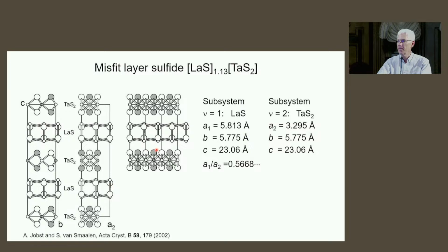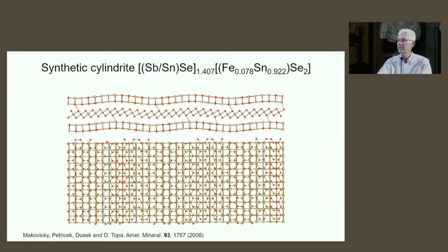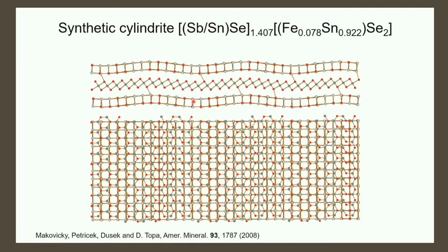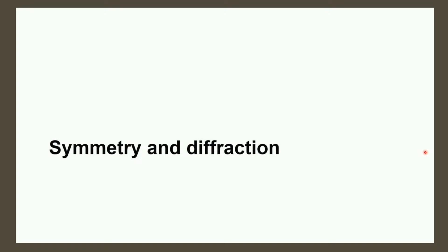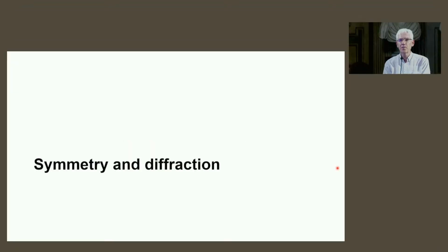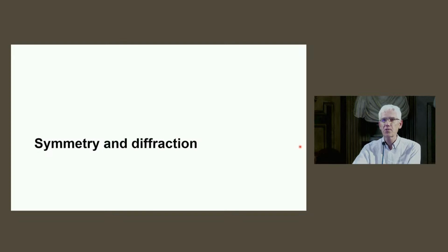And if we make several unit cells, you see again 3 unit cells of the tantalum disulfide do not match 2 unit cells of the lanthanum sulfide, and actually the ratio is an irrational number. I won't go in any more detail on these composite crystals, but they are also described by this superspace theory, and they are also famous in minerals. Again, this is synthetic cylindrite structure solved by Makovicky and Petricek and co-workers. And here you see the modulation wave much more strong than I've shown before. So that is a modulated structure with the superspace model of these wavy strings perpendicular to physical space.